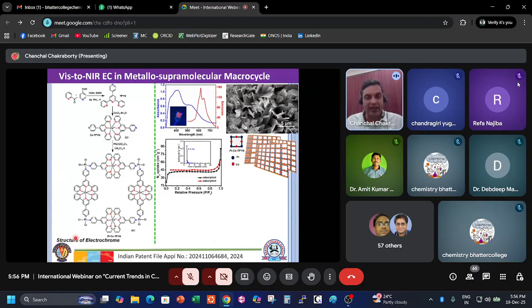oxidation or reduction. We also did a miniature box study with these materials, and we found that after 5 minutes of irradiation, this column is the orange or neutral state, and this is the black state. In the orange state the temperature went from 31 to 36 and 37. But the dark state does not show any temperature change inside the box. The window also has optical memory. After 15 minutes the blackish color is still there, so it can run without power.